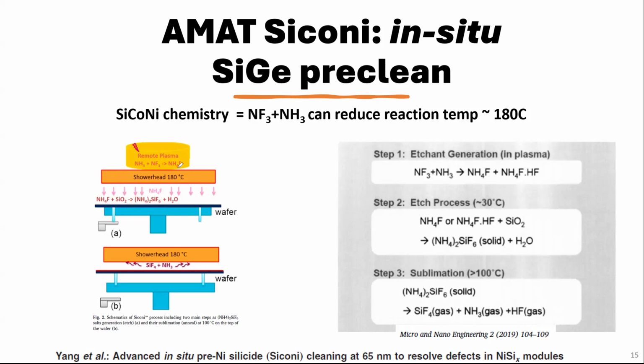And why use the chemistry? Because it would react to form these chemical reactions at 180 degrees Celsius. You don't need a pre-bake like people use, like 850 for hydrogen. So I want to clean my wafer. I will use 850 degrees Celsius hydrogen. That will clean the wafer. You will reduce this SiO2 into Si, etch, and vaporize away.